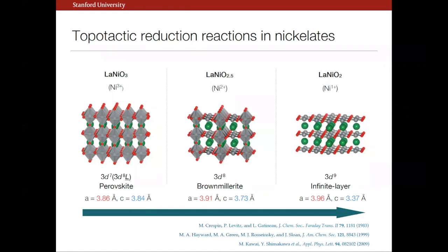And so the next key step, again in bulk, was to use metal hydrides, things like calcium hydride, by a group at Liverpool. What they did was intimately mix calcium hydride with their powders. It was real chemistry, right? They're dissolving things, filter paper, that kind of business. This really gave a firm foundation for the bulk powder synthesis and study of this material. And then about a decade later, another key step that we utilize is that the group of Professor Shimakawa at Kyoto University found that you could actually do the same chemical processing in thin films.